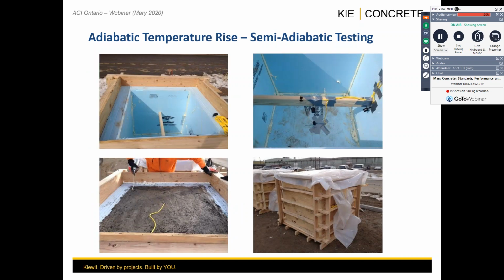Here I'm showing you an example of semi-adiabatic testing. This is the one that we typically do the most in major projects. Myself and many other field practitioners are using this method because it actually verifies the temperature rise of the concrete. You put 1 cubic meter into a super insulated box. You instrument the box with sensors. You leave it there for about 2 weeks, 10 to 14 days. And all the heat generated in that block can then be used in your thermal model to qualify the potential full adiabatic temperature rise.